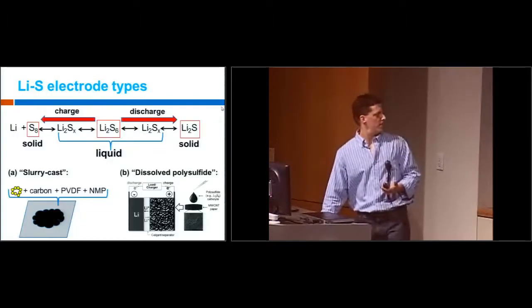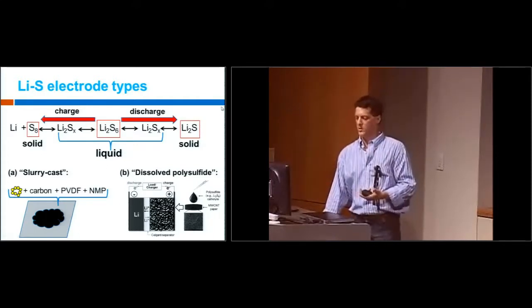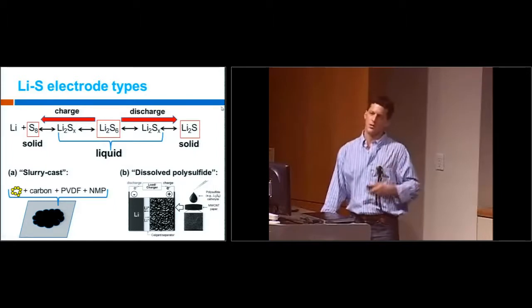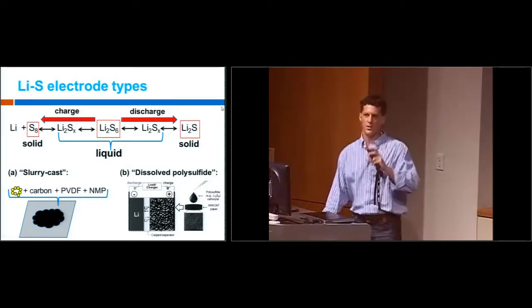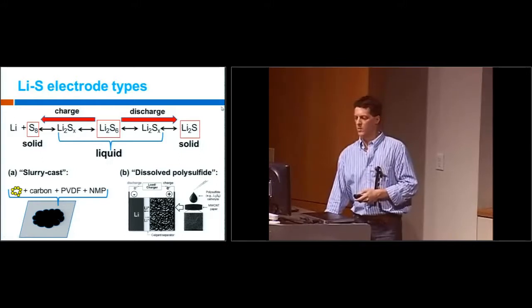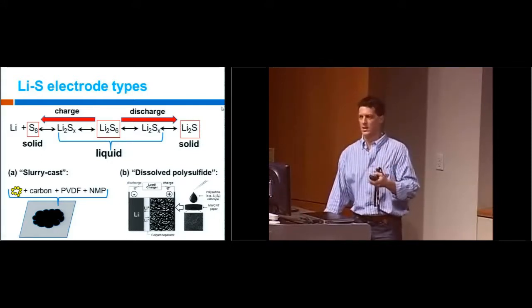Two of the most common configurations that we use in lithium-sulfur research. I showed the picture of the transition metal oxide, which is a very highly ordered material. In contrast, with lithium-sulfur, the first generation configuration of the cathode was to take elemental sulfur, some sort of conductive material, typically conductive carbon or a conducting polymer, and a binder, something that just holds it all together, and then a solvent to suspend it. You try to mix it as well as you possibly can, either mechanically or with milling, and then cast that onto an aluminum current collector, and this is how you extract the electrons.